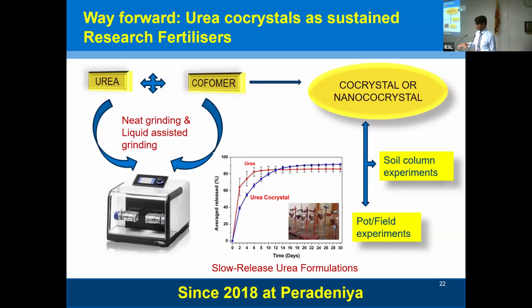our research group published the very first paper. So we used these concepts to tune the urea release. In this concept, we used urea and another third-party material, and we ground these 2 materials together. It's a solid-state reaction to come up with a novel solid-state material. Here, in the presence of a very minute amount of liquid, which acts as a catalyst, it's a solid-state reaction, so no solvent is involved. It's a green synthesis. And then you can even convert them into nanoscale. And then we carried out the same set of experiments at lab scale, pot trials and field trials. And then we came up with a novel fertilizer. We opened up this novel fertilizer material to the field.